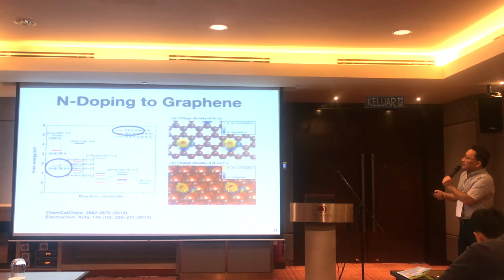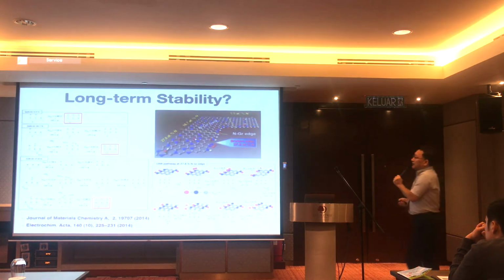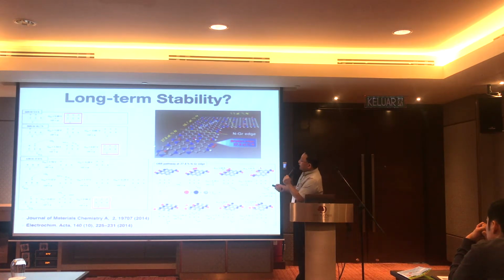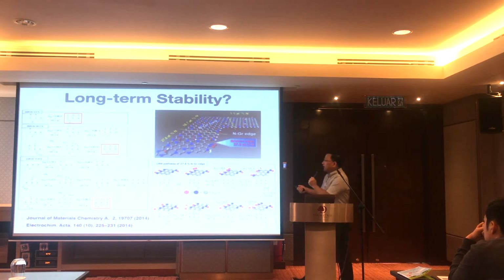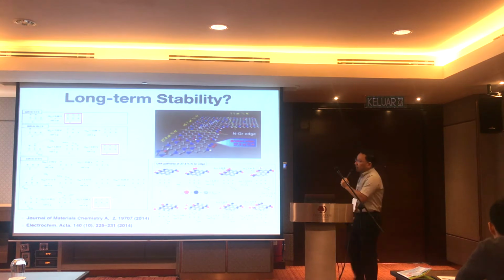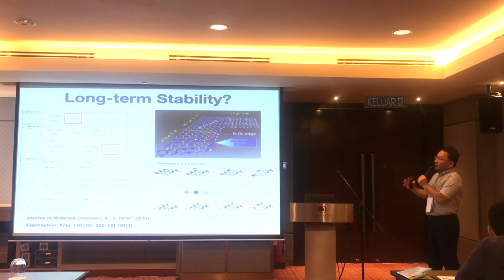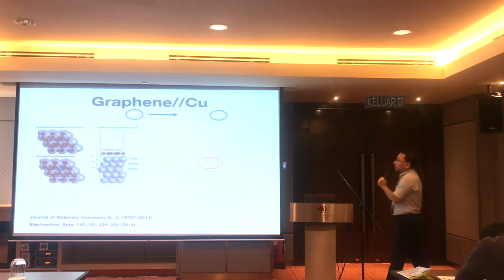Very strange. Okay, but we found that nitrogen-doped graphenes are, of course, good. The activity is almost the same as platinum. The problem is that if you design graphenes, there are always edges. Single-layer carbons are already edgy, but this edge is not good because it is always poisoned by many different chemicals, hydroxyl groups, and other materials. Once they are poisoned by these chemicals, the framework is easily destroyed. It's not stable. So even though graphene got the Nobel Prize, that material is not good for catalysts for oxygen reactions.